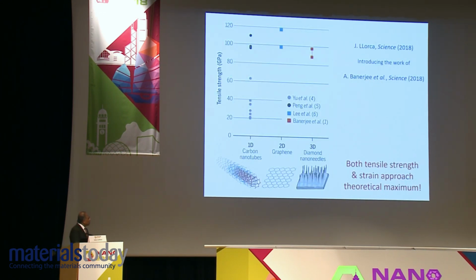When these findings were reported a couple of months ago in Science, in an introduction to our article, Professor Javier Llorca from Madrid presented this figure in a perspective which was very interesting. The maximum tensile strength that has been achieved in one-dimensional carbon, which is carbon nanotube, is of the order of about 100 gigapascals. In 2D carbon or graphene, the maximum strength that has been shown is of the order of up to 120 GPa. In our experiments in nano needles, the maximum strength in 3D that we demonstrate is of the order of about 100 GPa. And this is an interesting way to look at this.